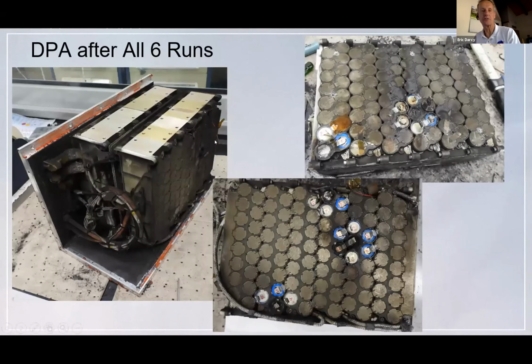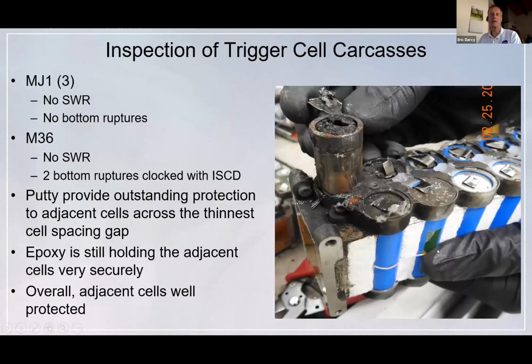We were able to charge and discharge this pack in between runs in order to clean up the pack and refresh the flame arresting features to make it valid for the next test. So, the summary: when we took apart this pack, we inspected the trigger cells. We didn't see any sidewall rupturing on any of the 6 cells. And we did have some bottom rupturing in the M36 cell. But we were able to handle that. As long as it doesn't go through the sidewalls, we're good.